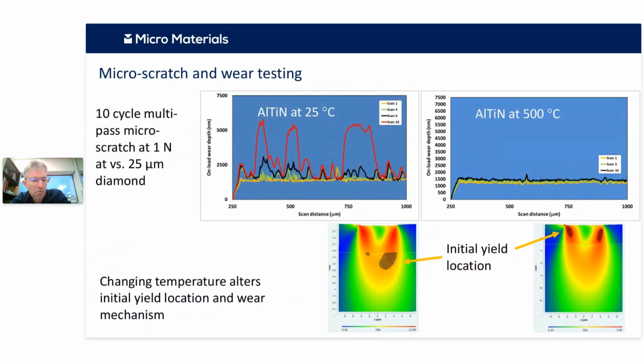So this is much older work now. This is going back to the original test, maybe 2004 or something like that. So here we're using microscale scratch testing, again looking at, in this case, PVD coatings for cutting tool applications. And if we test this coating in a multi-pass scratch test at room temperature, then after a few cycles, you can see these localized failures in the coating, and essentially it's delaminating in certain regions.